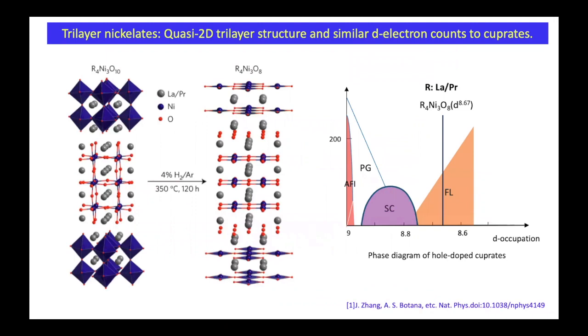Okay, in the last few minutes, I want to go to the nickelates. We are working with also hydrogenated samples. They start as single crystals of a 4310, three nickel oxygen layers. John Mitchell, who works with us, is able to remove oxygen, go to the 438. It's a line compound. If you just count from valences, you expect the doping level would be here, slightly overdoped, something like 8.67. And I'm overlaying that on the cuprate doping phase diagram.